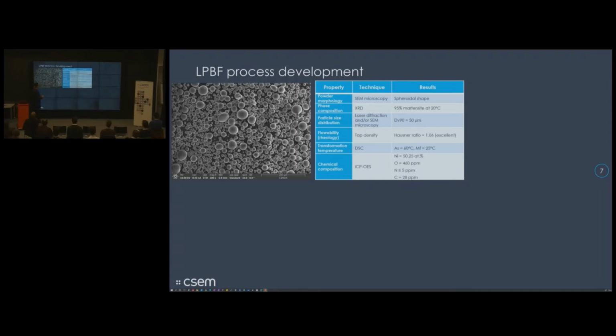So we have qualified the powder based on its morphology. It needs to be spheroidal, so it has good flowability. The right phase composition, so at room temperature, we want it to have martensite. The particle size distribution needs to be right so that it's printable. If it's too big or too small, it wouldn't work for laser powder bed fusion. The right flowability, in this case, it had an excellent flowability, manifested by the Hausner ratio that is very low.